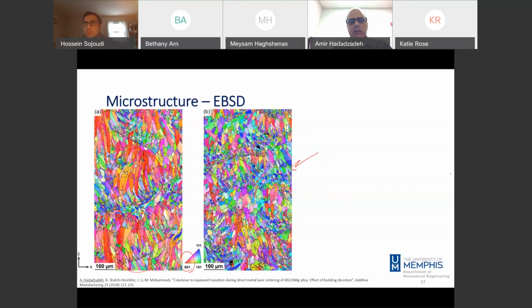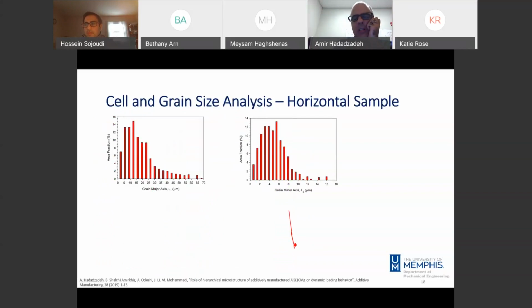the material we used was aluminum silicon, about 10% silicon and a little bit of magnesium. The reason we use that system, again, as I mentioned, is because if we recall the aluminum silicon phase diagram, if I am able to draw it, that composition is close to the eutectic composition. So here is the eutectic composition, silicon, about 11% of silicon.